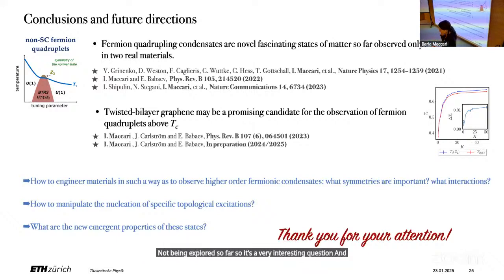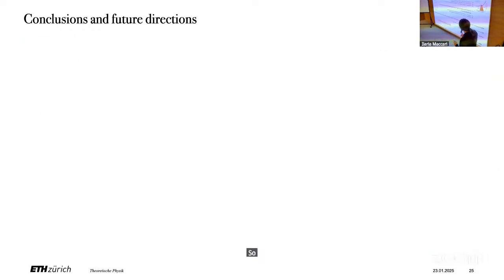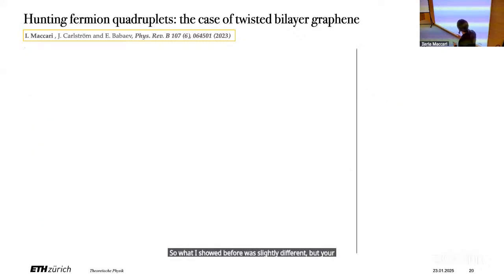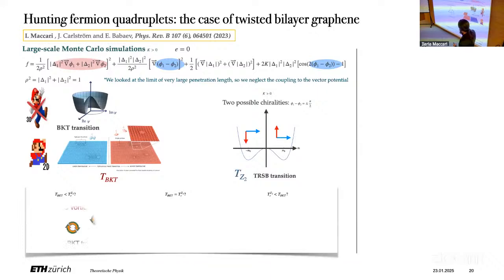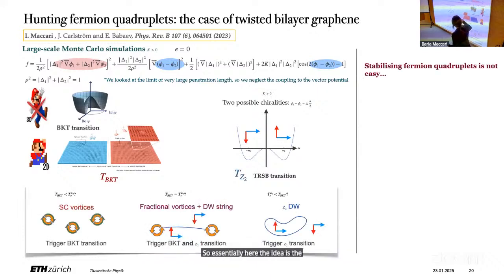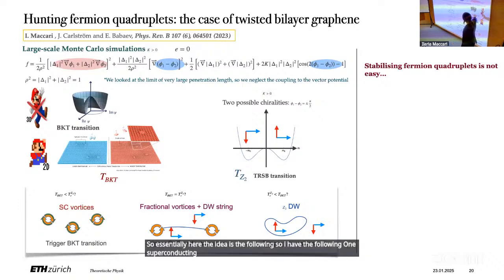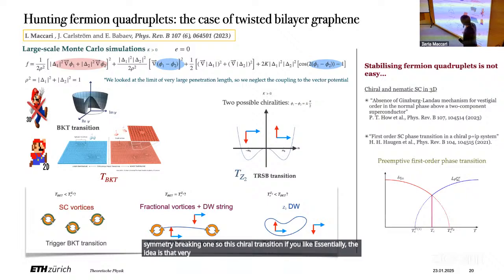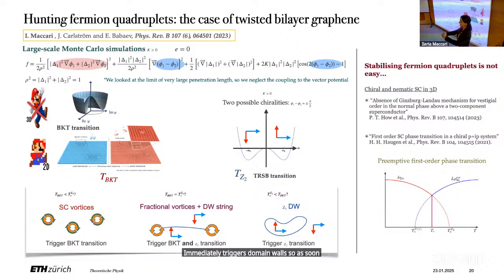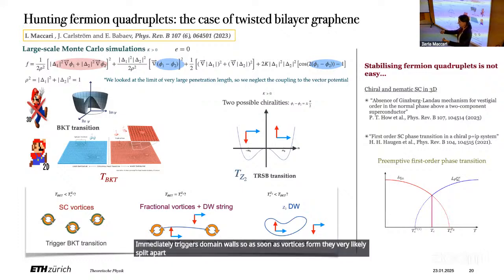And about the first order phase transition, what I showed before was slightly different, but your question is still very interesting, so let me point it out here better. So essentially here, the idea is the following. I have one superconducting phase transition and one transition which is this time reversal symmetry breaking one. So this chiral transition, if you like. Essentially, the idea is that very often you can have that the proliferation of, for instance, in this case, vortices immediately triggers domain walls. So as soon as vortices form, they very likely split apart in fractional vortices, and then you have no more room for these phases.